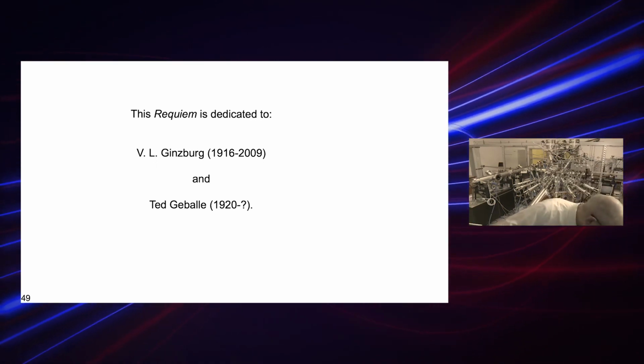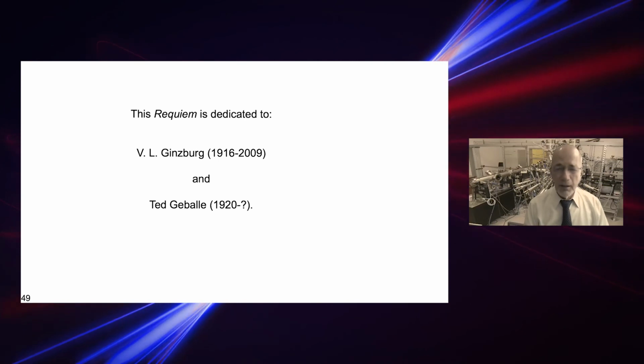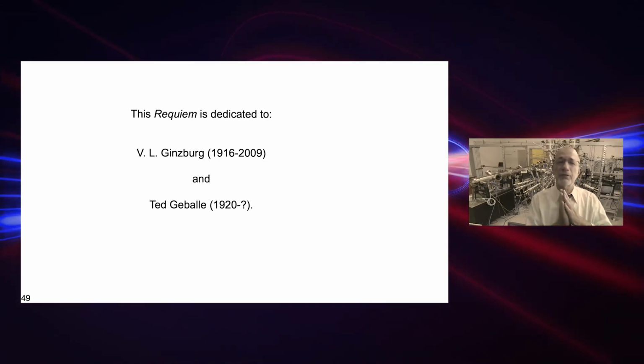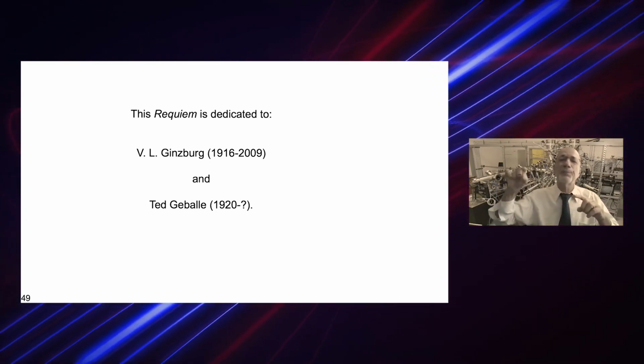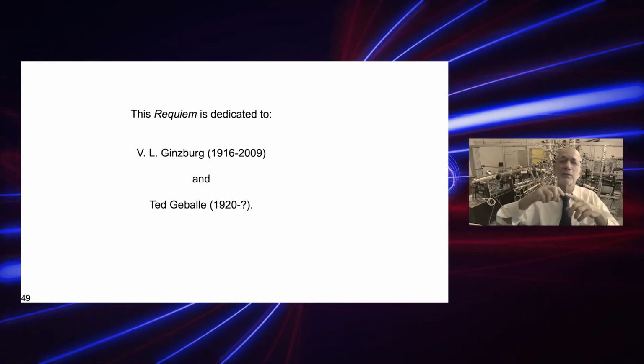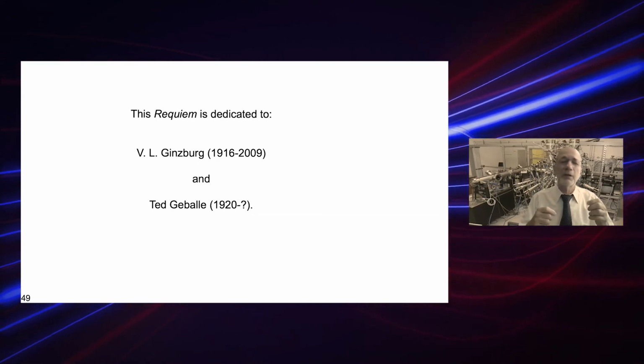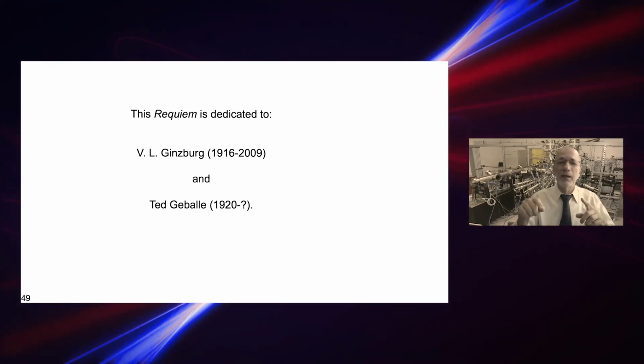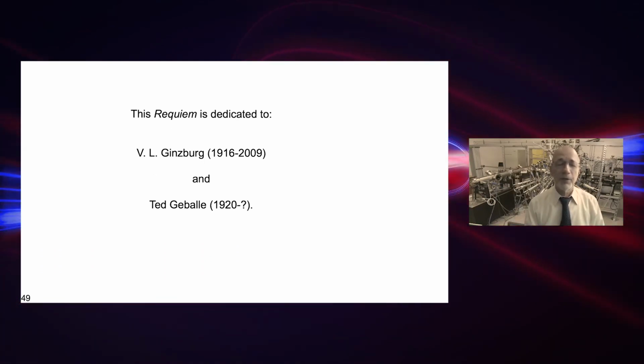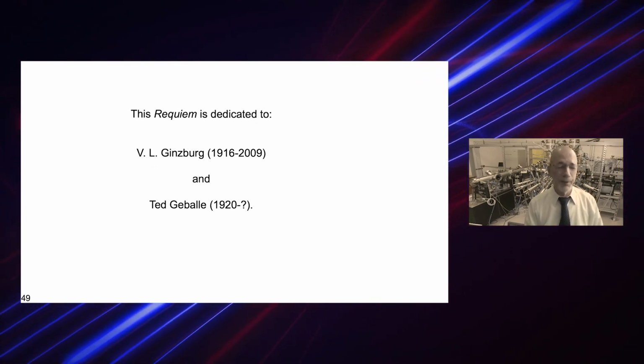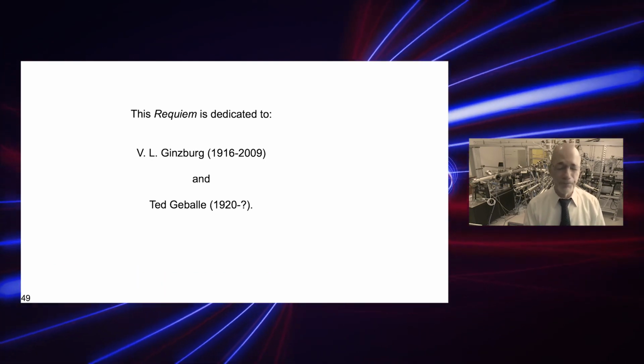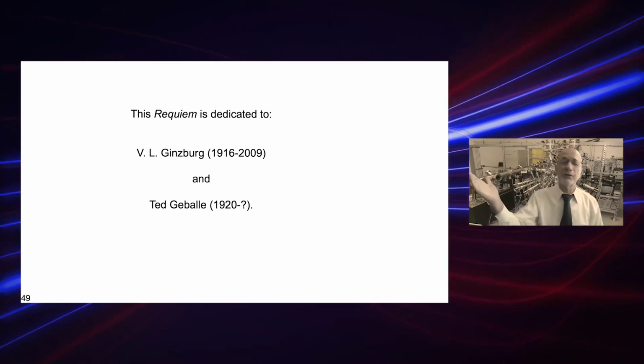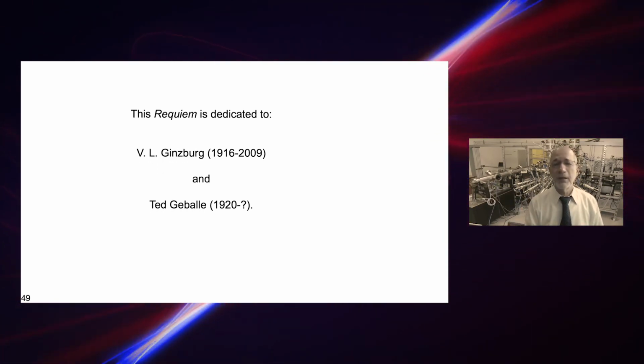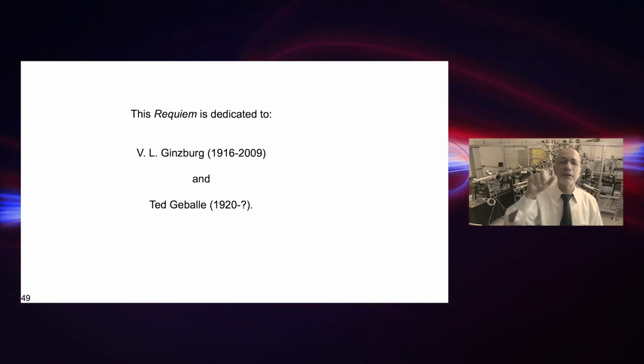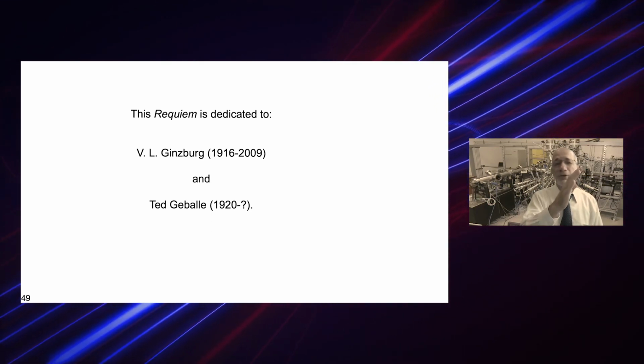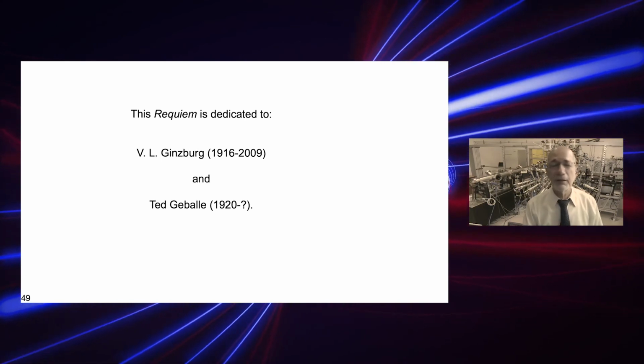Oh, this is a good question. This is just a model. If you restrict yourself just to rho versus T curves, these are very simple curves. You can fit them with a polynomial of second order. You can also fit it with rho equals rho 0 plus a times T to the b. This was done a decade or two ago, for example, by Lia Krusin-Elbaum, a very prominent researcher in superconductivity, and she showed that she could fit all these curves and the doping dependence that way. What was changing in that case was basically the exponent, which was changing continuously from 1 to 2.